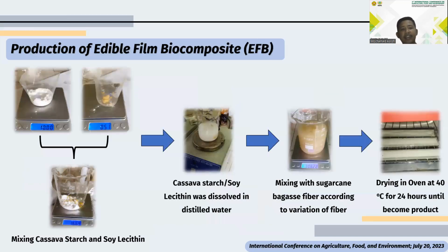If we have already prepared the fiber, we move to the production of edible film biocomposite. The first one, we mix cassava starch, soy lecithin, glycerol, and distilled water, dissolved on a hot plate magnetic stirrer at 400 RPM for 10 minutes. After that, we mix with the sugarcane bagasse fiber according to the variation of fiber. In this research, we varied the fiber at 1 to 3% of the starch weight.